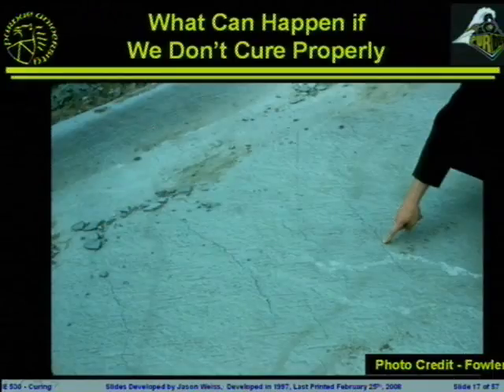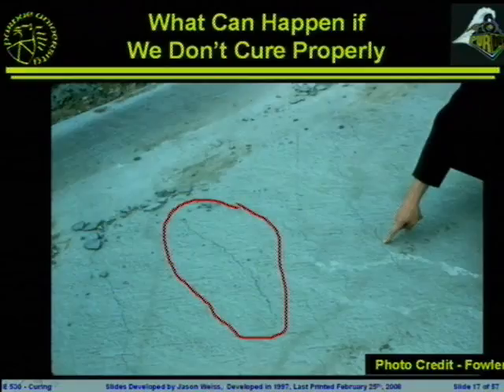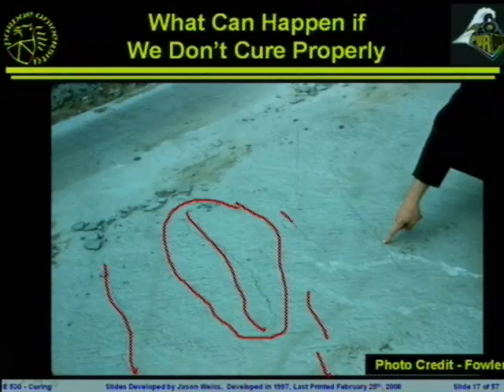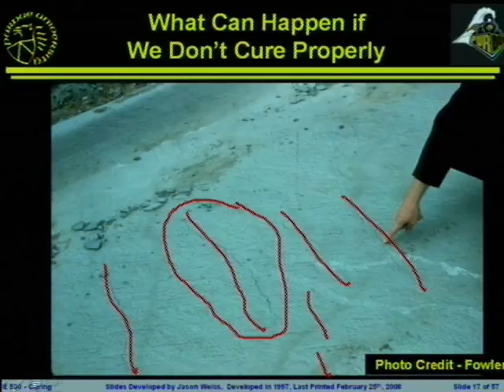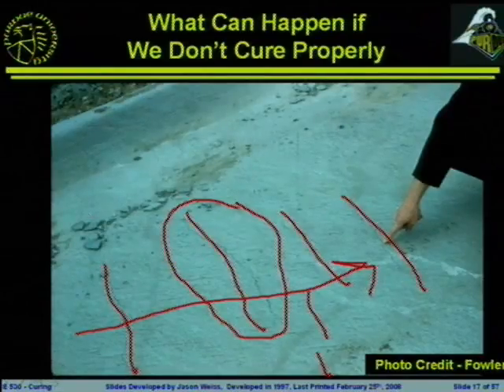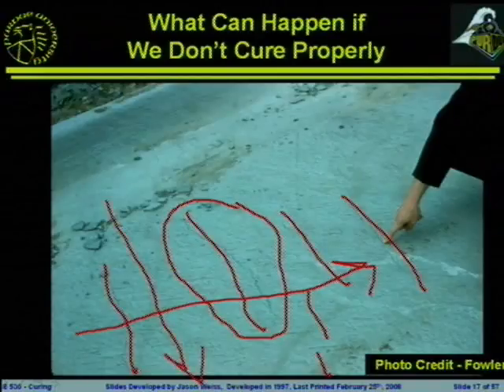Well, you get a concrete surface that looks like this, where you can see a lot of these cracks that are forming. They're relatively parallel to one another. They're relatively random in general orientation, although in this particular case you can see they sort of line up, and we would guess that the wind is going in this direction and there's reinforcing steel going in this particular direction. This is pretty typical of what we see as plastic shrinkage or plastic settlement cracking.